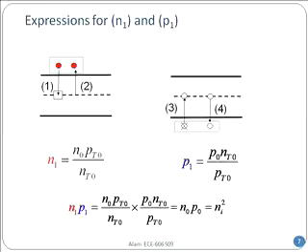This is always true. And therefore, since N0 and P0 in equilibrium is equal to Ni squared, somehow if I can calculate N1, I'm done, because I can calculate P1 by using this relationship. Remember, this is where the quantum mechanics hides in Ni squared, because it is the effective density of states, Nc and Nv, and the band gap in the exponential. Do you remember that? So we are carrying along the quantum mechanics, just in a disguise. So you don't see it, but everything is coming with us.